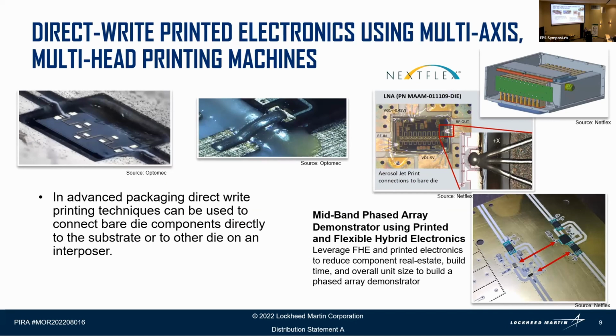What I'm showing here, in the top left and the middle sections, are two bare die components. One is sitting in a pocket on the left, and one is sitting on the substrate surface in the center. We've demonstrated here, and I can use my pointer, this trace has been connected using the aerosol jet printing process, and we've made connections to the substrate. On the other center one, what we did is print this dielectric ramp onto the device, and then we printed the conductive trace over the top of that to make the connection.